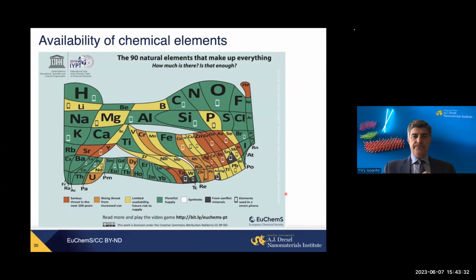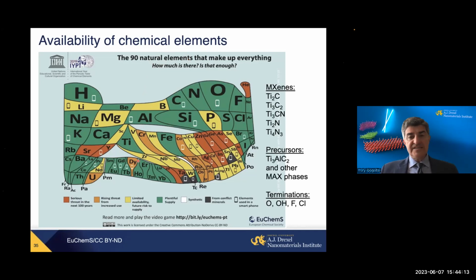We can process materials in quantities, making it a really scalable technology for many applications. We can have materials dispersed in water, processed from water, which is the cheapest solvent. But what is also important, if you look at titanium, aluminum, silicon, carbon, nitrogen, oxygen in the backbone, fluorine, chlorine, sulfur termination, those are among the most abundant elements, which we have in more than sufficient supply. Even vanadium, zirconium, niobium, molybdenum are close in availability. So what it means is that we can really make them in quantities.